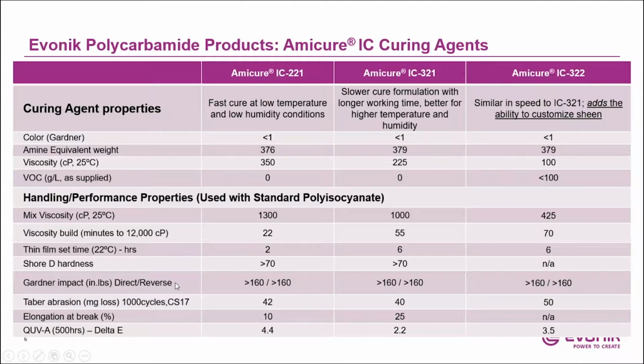And also impact resistance, so in terms of flexibility, you see very good flexibility. You get very high flexibility, greater than 160 inch pounds for all these coatings. So it's unique in terms of getting very high hardness, but also very good flexibility as well. So these coatings are very tough, and that makes them very durable. Taber abrasion. So you see the values for Taber abrasion are around 40 milligrams loss, more in the area of what polyurethane coatings bring. So very good abrasion resistance.